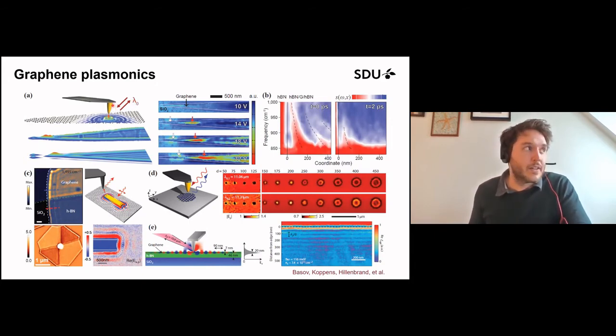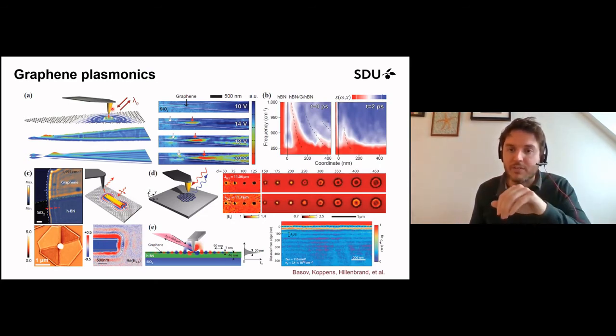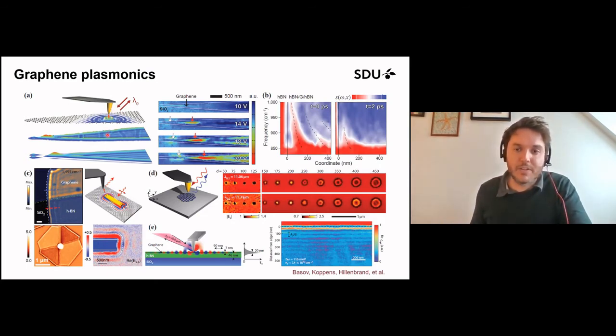So in this technique, we have a metal tip that effectively excites the plasmons, right? And they propagate away and they come back, and then you can see them from the light that's outcoupled. And then you move the tip around as you're doing this, and you can create a map of these charge density oscillations in your 2D material.